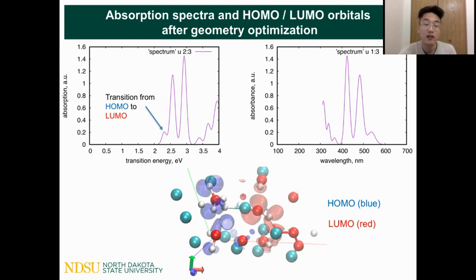As you can see here, the occupied orbital, which is in blue, is primarily localized on hydrogen atoms. However, their charge density tends to be distributed on the negatively charged oxygen, which corresponds to the red domain. Next, please.